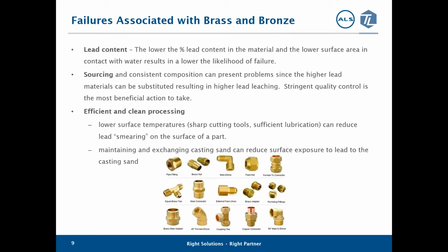Historically, the failure mode for brass and bronze materials has been related to the leaching of lead. Exposure to lead has been well studied, and the negative effects due to lead are well known. We can do many webinars on the leaching of lead from brass and bronze or the negative health effects due to lead. The good news is that manufacturers continue to decrease the use of lead materials as well as finding substitutes for leaded brass and bronze. However, there's still a significant amount of progress to be made in replacing old infrastructures and continuing to find ways to reduce lead exposure to humans, particularly to children.